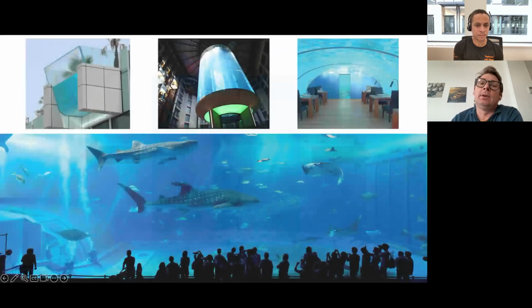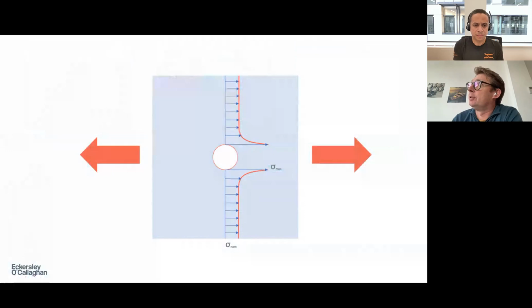And after doing a few very simple calculations, we're talking 10, 12, 13, 14 sheets of glass for that wall panel. And while glass is a great material, it can chip, it can crack. And the consideration of what happens if there's small damage in one of those panels would be a very difficult replacement.